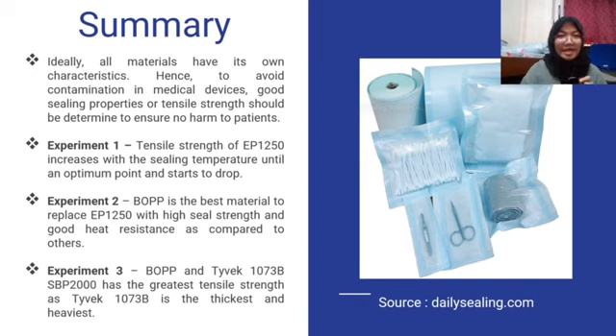For experiment 1, the tensile strength of EP1250 increases with the sealing temperature until an optimum point and starts to drop. But the temperature must be high enough to activate the sealant layer without scorching the material's surface or causing it to become excessively transparent. For experiment 2, among all of the recyclable films, BOPP is expected to have the highest seal strength and good heat resistance. Consequently, it is the best material to replace EP1250, which is non-recyclable film, based on our research studies. For experiment 3, BOPP and coated Tyvek 1073B SBP2000 has the greatest tensile strength, as the Tyvek 1073B SBP2000 is the thickest and the heaviest. Therefore, it will also offer the highest tensile strength, best puncture resistance, and the durability is high, suitable to be used for sharp medical device packaging. That's all from us. Thank you.